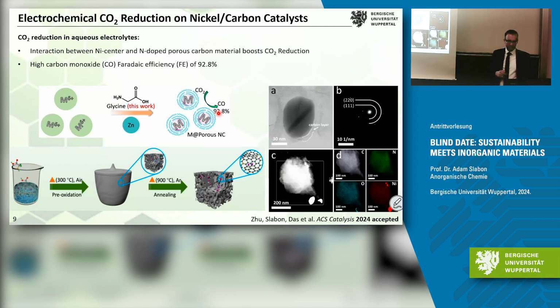Again, we need spectroscopy for this and TEM. We see here a single nickel nanoparticle, and here you can see the matrix of the carbon doped with nitrogen, or rather substituted with nitrogen. And you see here you have the particles. So a nice catalyst. What about the performance in terms of currents?